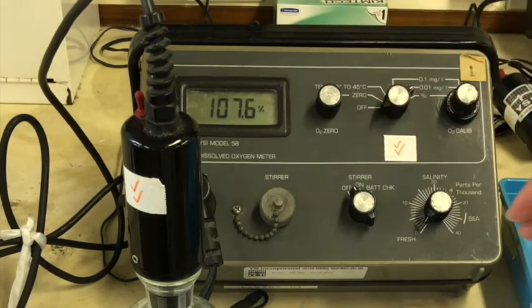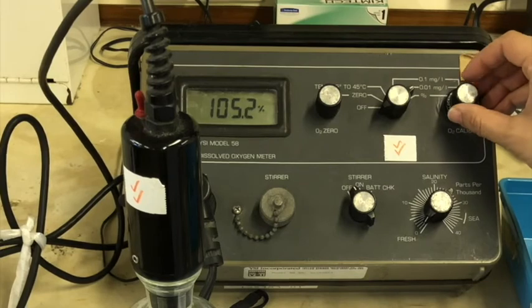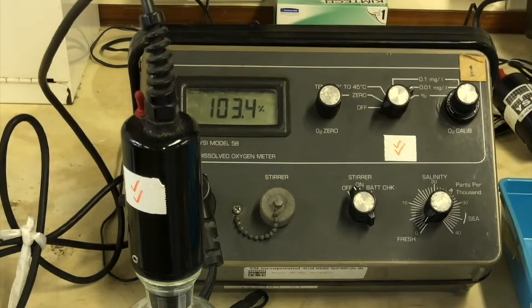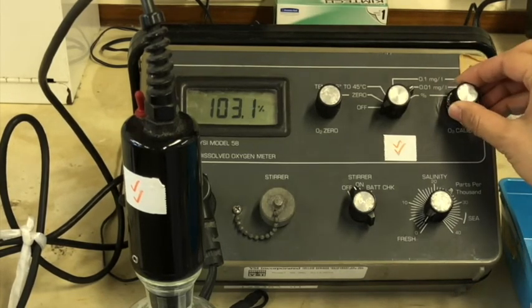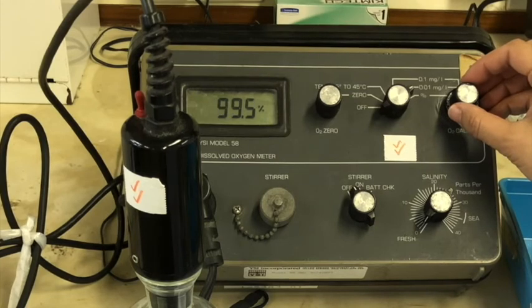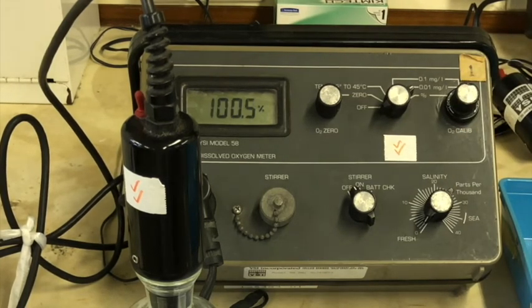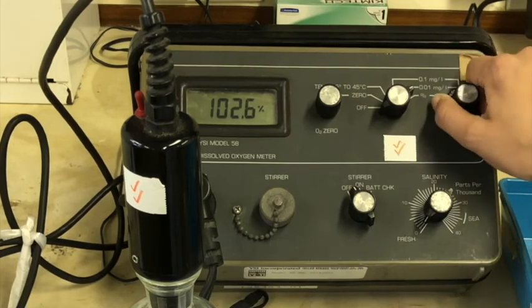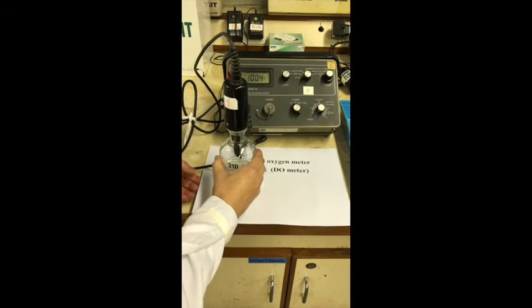As you can see, the reading is dropping. Adjust the knob slowly until it reaches 100%. The fluctuation of the readings indicates the oxygen membrane is getting older. The knob can be adjusted clockwise or anti-clockwise to get the numbers to reach 100%. As the fluctuation gets small and all the numbers are around 100%, it means the setting for saturation is finished. You need to lock the knob after setting 100% and change over for the sample measurement.